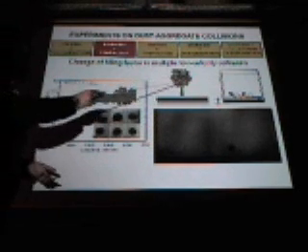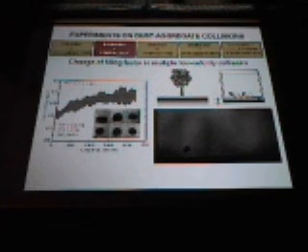We took a dust aggregate, again a cube, put it on a shaker, which had an amplitude of 100 micrometers and a frequency of 100 hertz, and we shook it all the time. And what we see is, at the beginning, it's a cube, then the corners are eroded, so they are definitely lost, they break off the aggregate, so we lose mass in that place. And afterwards, the mass stays constant, we measured that, and the aggregate is getting smaller and smaller. So it's getting more compact, so the filling factor increases.